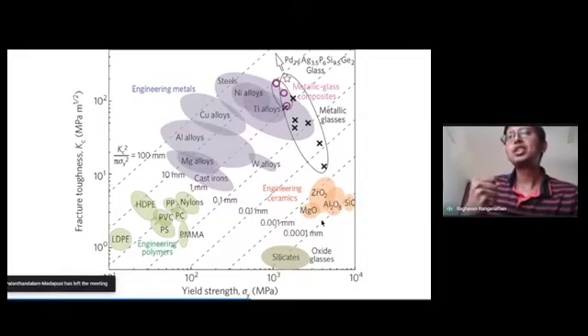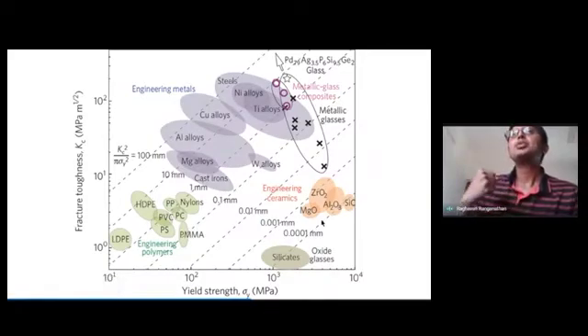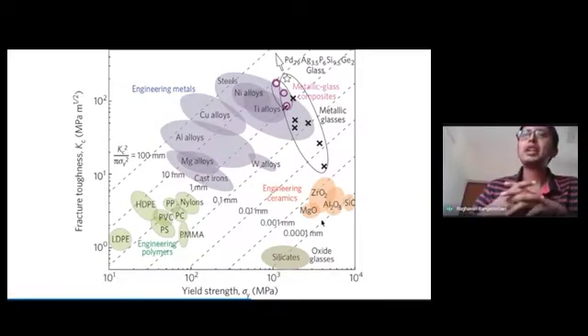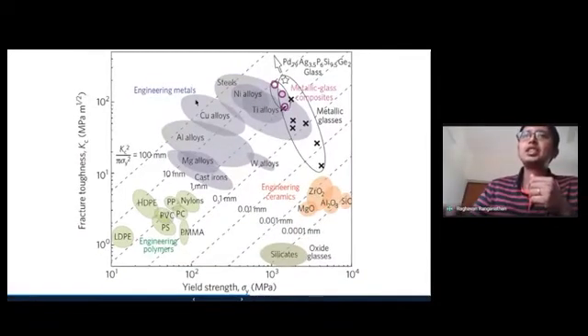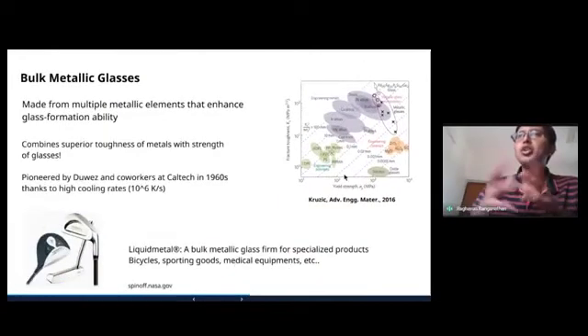So what Duwez and co-workers came up with is to basically amalgamate the toughness of metals and the strength of glasses. So they engineered novel metals that are made up of these metallic elements, one of which is listed here. So this is a glass that's made up of palladium, silver, phosphorus, silicon, and germanium in a certain composition. And these form metallic glasses which show simultaneously high fracture toughness and high yield strength. Okay. So this spawned a very huge active area of research.